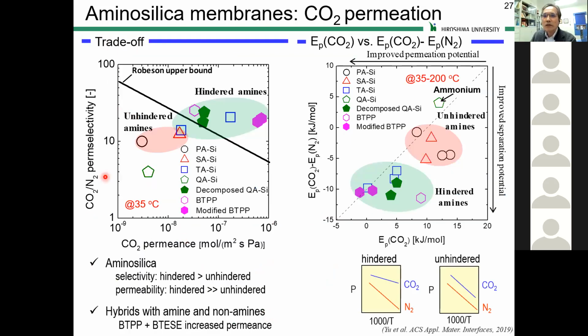Here we have a trade-off of CO2 nitrogen separation. Perm selectivity is now plotted against CO2 permeance. This pink area indicates unhindered amine. Blue indicates hindered amine type over here. As you can see, selectivity is higher for hindered amine. Permeance is also higher for hindered amine. Even hybrids with amine types with the BTESE indicate very high permeance, close to 10⁻⁶, with enough selectivity of CO2 over nitrogen, around 20 or 30.